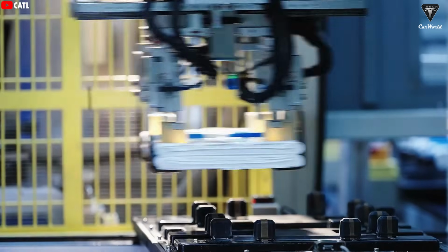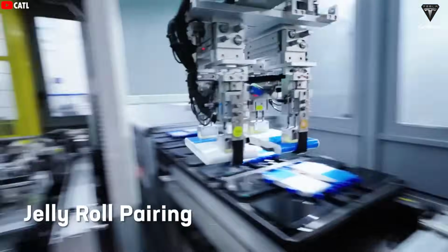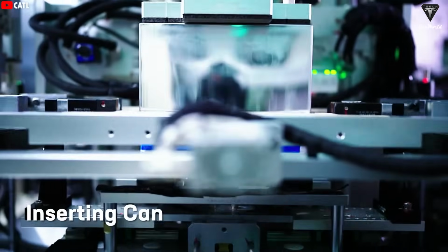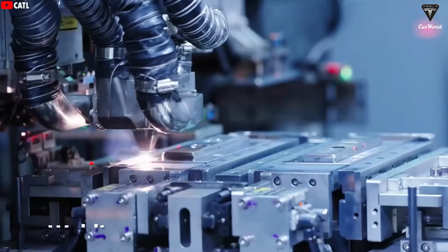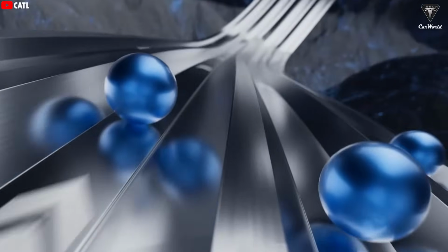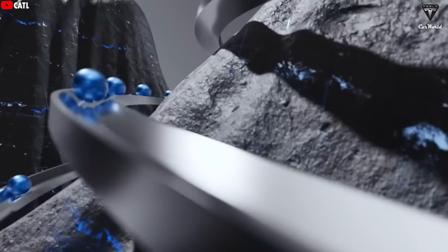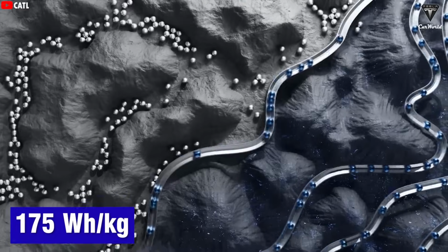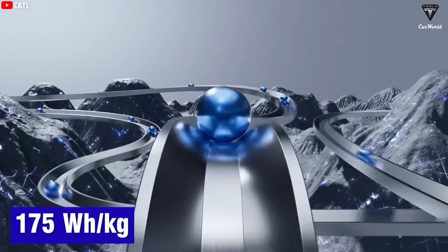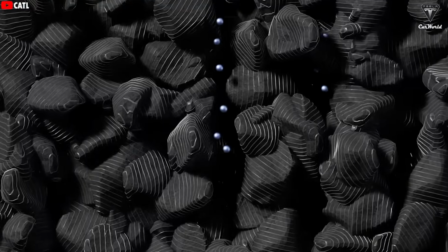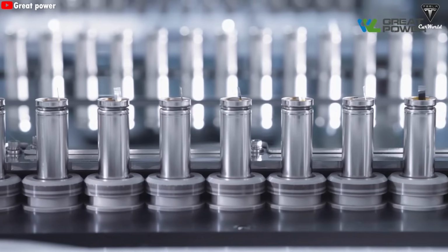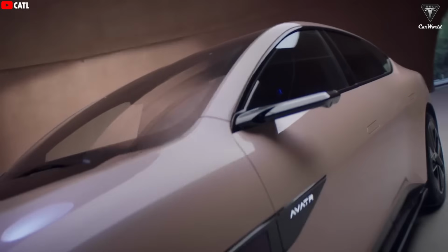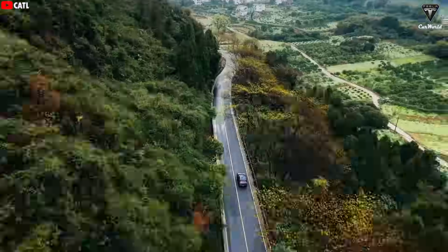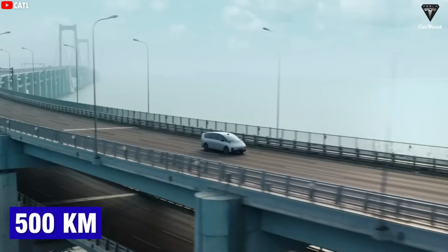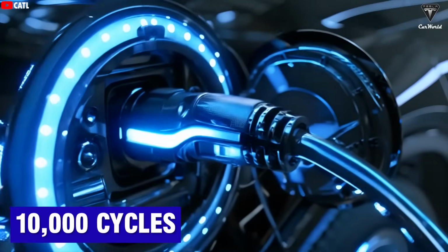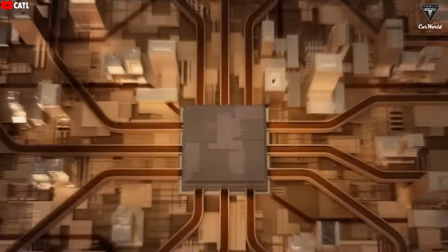But now, CATL's Naxtra battery has broken the performance boundary of the material itself, achieving mass production of sodium-ion batteries for the first time. Specifically, CATL's Naxtra EV battery achieves an energy density of 175 watt-hours per kilogram, the highest among sodium-ion batteries worldwide and comparable to LFP batteries. This enables the Naxtra battery to help EVs achieve a range of 500 kilometers and can achieve more than 10,000 cycles, significantly reducing maintenance costs.